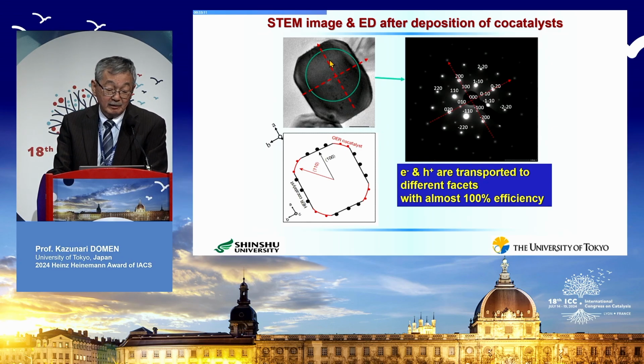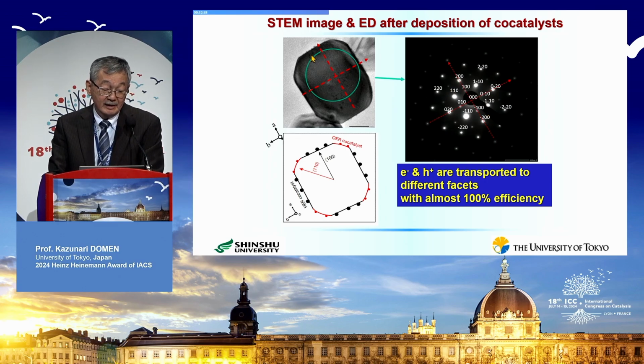This is one particle of our photocatalyst, and sorry, this length is 100 nanometers. And then from this part, we obtain this kind of electron diffraction pattern. And from this electron diffraction pattern, we can identify that this flat facet and these flat facets are 100 facet and their family. And I hope that you can see very small particles that exist on these facets. And all of these particles are actually rhodium and chromium core-shell structure for hydrogen evolution.